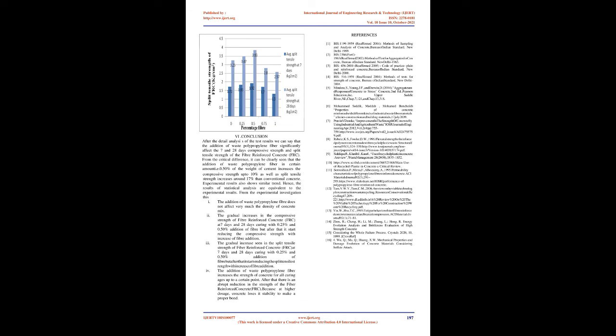Hence, the results of statistical analysis are equivalent to the experimental results. 1. From the experimental investigation, the addition of waste polypropylene fiber does not affect the density of the concrete mix very much. 2. The gradual increase in the compressive strength of fiber reinforced concrete, FRC, at 7 days and 28 days curing with 0.25% and 0.5% addition of fiber, but after that it starts reducing the compressive strength with increase of fiber addition. 3. The gradual increase is seen in the split tensile strength of fiber reinforced concrete, FRC, at 7 days and 28 days curing with 0.25% and 0.5% addition of fibre, but after that it starts reducing the split tensile strength with increase of fibre addition.